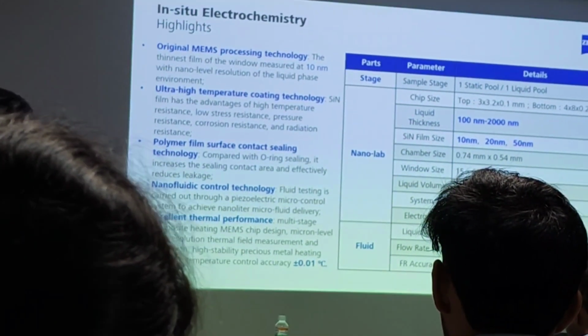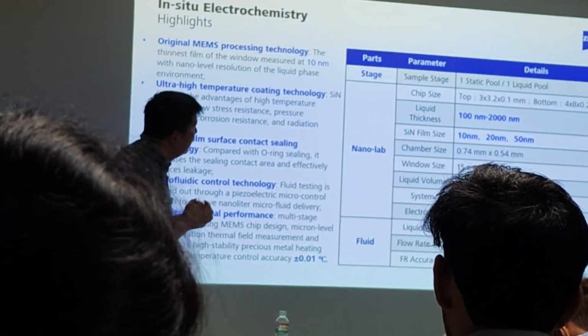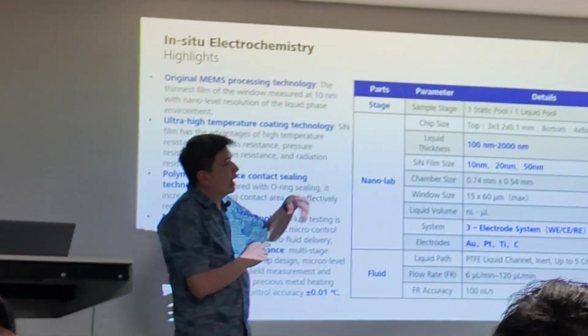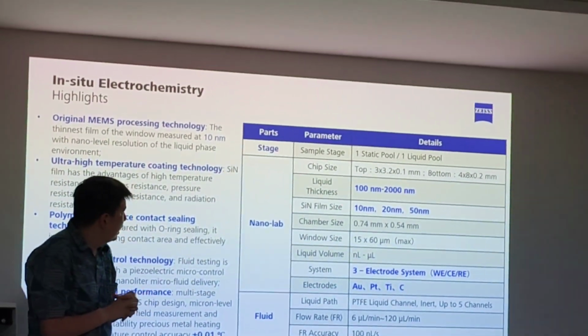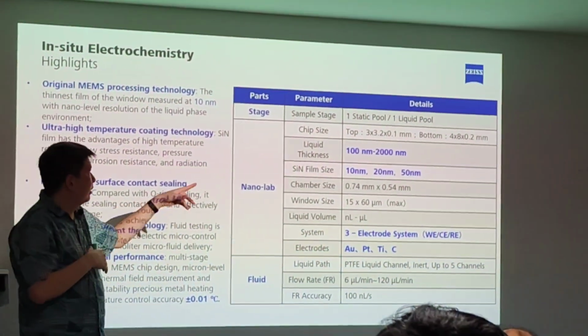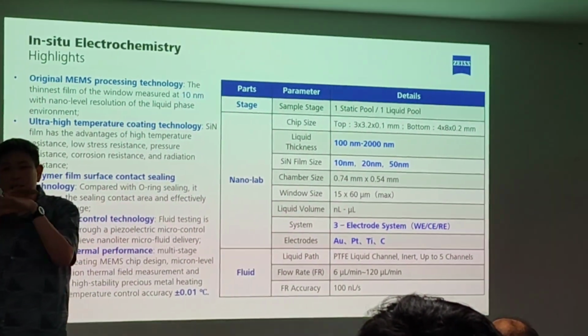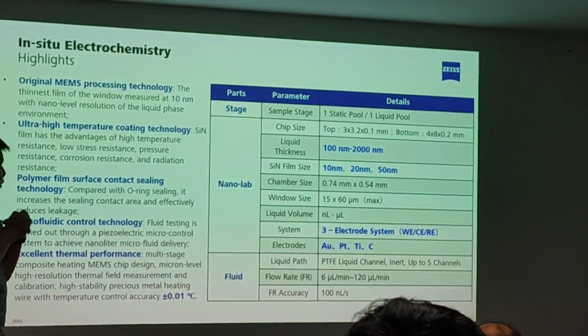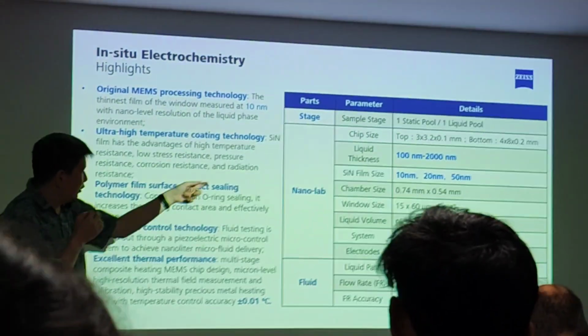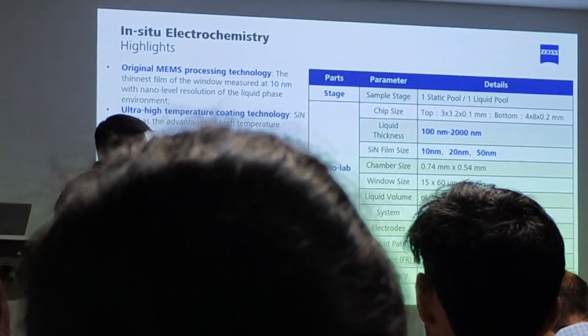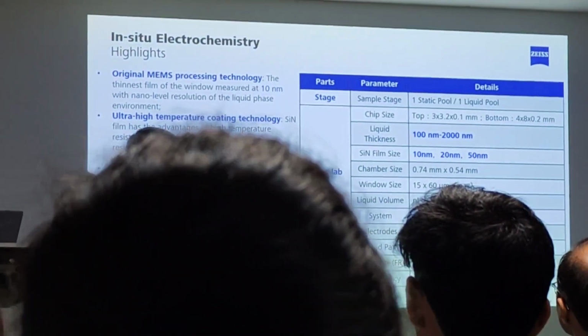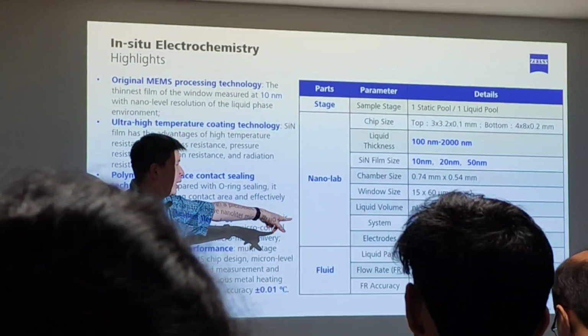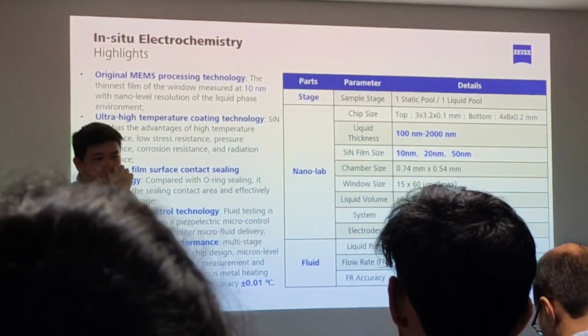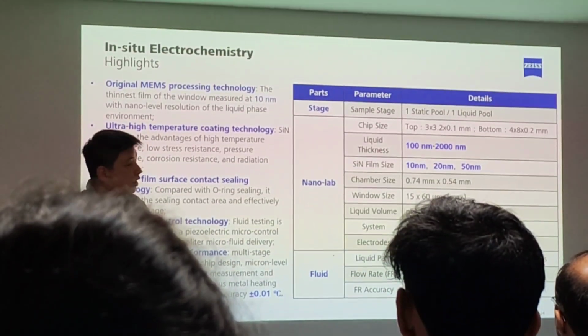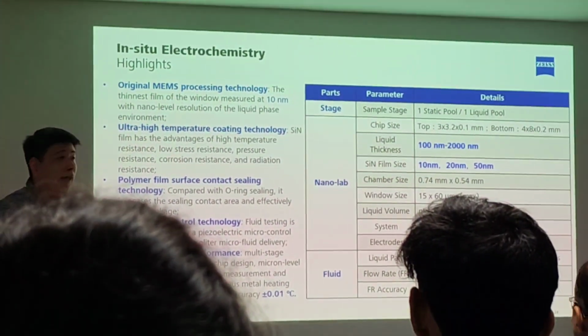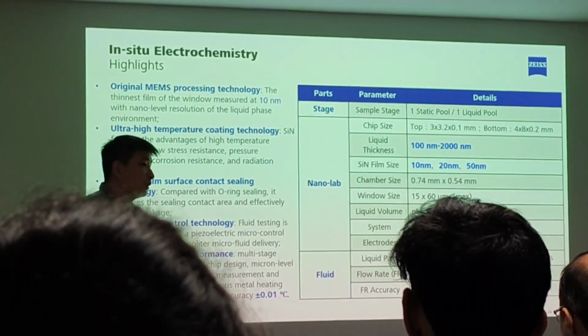So to give you a sense of what we are talking about, the liquid thickness is only in the nanometer range, 100 to 2000 nanometers. We are covering it with this material called a silicon nitride film. So it's a very thin film, alright, to cover the materials. And the chamber size, you can see it's sub-millimeter. It's 1 mm kind of thing. Liquid volume in the microliter. We can put a 3 electrode system. Electrodes we can choose between gold, platinum, titanium, carbon, and of course, reactive electrode is not there yet, but who knows, in the future we can make some reactive electrodes also, like copper or something.